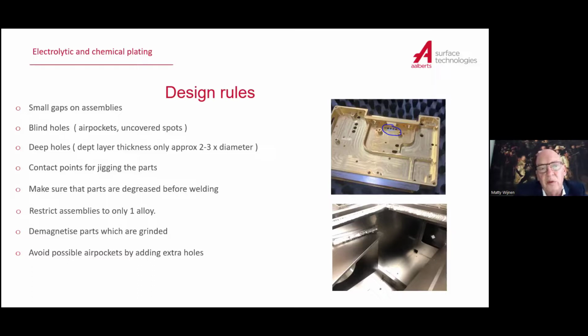If you put them together, what happens is that during the pre-treatment, during the manufacturing, there's oil on the inside of those plates. You put them together and you send them to us. Now, we put them in a degreaser, and that bath is 50, 60 degrees, and we remove all the oil on the outside surface. Then we go further to a chemical nickel bath, which is 90 degrees. Of course, when a bath is 90 degrees or 50 degrees, the part expands a little bit more. That means the gaps get a little bit bigger. The oil which is in between comes out in that bath and will make sure that on the edge of your gap,